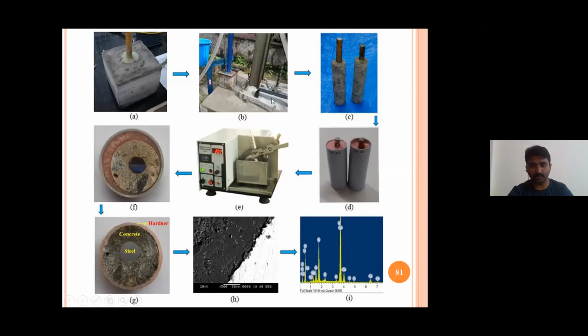Then I took the core, looks like this. Apply the PVC pipe and rapid hardener. Use a slow speed diamond saw cutter to cut the samples. Do not use high speed diamond saw cutters. Once you use low speed diamond saw cutter, this is how the sample looks. Go for epoxy impregnation.